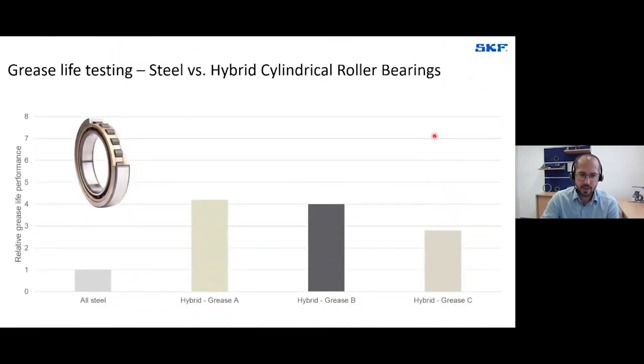And a very similar effect could be identified on cylindrical roller bearings, where we have tested basically similar or the same greases, and the grease life performance or increase behaved a bit different, but still it shows that the factor of 2 is definitely justified, but it can go up to higher factors of 4 in those tests, for example, but it can go up even higher.